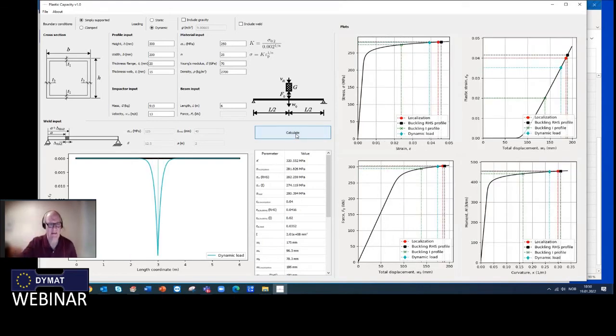Then you see the plastic strain along the beam. And here you see the stress strain curve. And here you see the force acting between the impactor and the beam. And if you look at this, we see that here is the load situation I've chosen. And here I get diffuse or localized necking, which is the red dot. And here I get buckling of the rectangular hollow section profile in the compression flange. So here it seems to me that everything's fine.